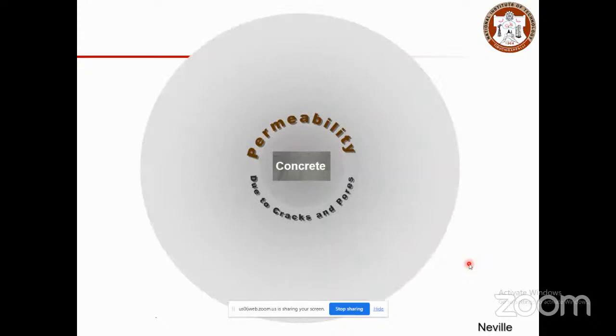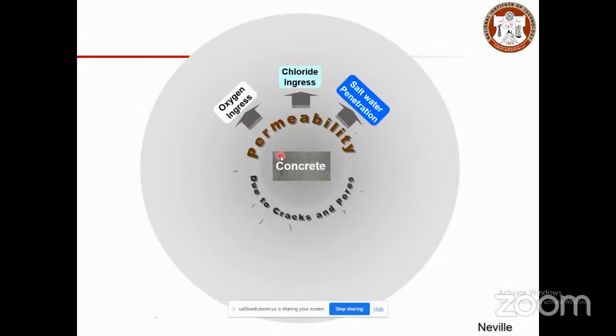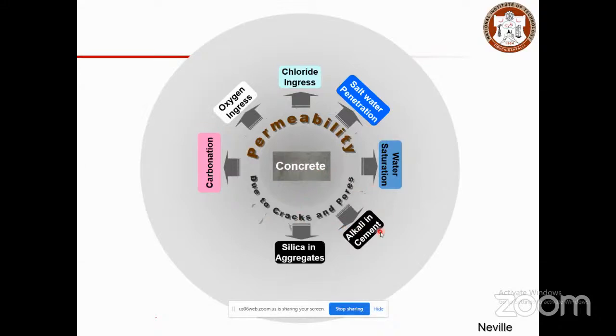Now concrete structures will all be porous. It is a highly heterogeneous material. The pore connectivity will lead to permeability, and if the concrete cracks, so you can see mild crack formations, that may lead to chloride ingress and oxygen ingress to your material. Depending on the environmental conditions, you may have saltwater penetration, carbonation, and water saturation, and these are external conditions. And if you talk about the pores and cracks, the materials that you have may have some alkali content in cement, and some other ingredients that we use in concrete.